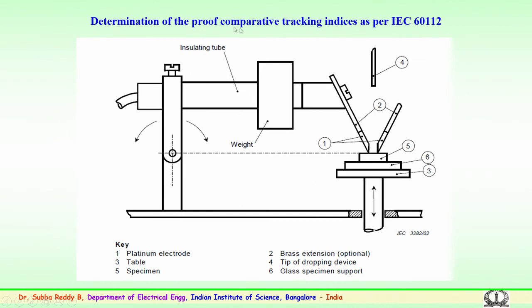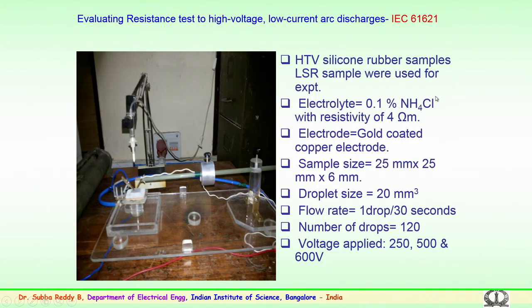So, the entire arrangement has to be fabricated for studying the comparative tracking index. This is with reference to the IEC 60112 standard. So, we have tried to fabricate a similar arrangement. You can see here 2 electrodes, especially gold coated electrodes, have been used at a known distance, and the droplets of the contaminants are supposed to be dropped at regular intervals. This is the dropper arrangement, and the voltage